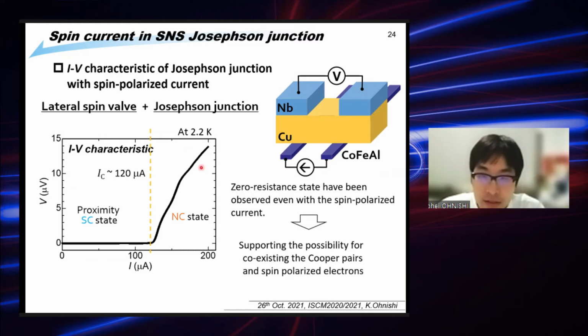So this result indicates that even though we use a spin polarized current, the Josephson junction showed the superconducting state. This result strongly supports the possibility of coexisting Cooper pairs and spin polarized electrons in this copper layer.